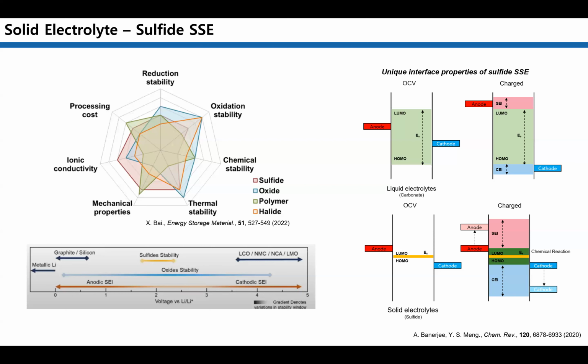In carbonate electrolyte systems like NCM and graphite, the HOMO and LUMO levels are outside the stability window, resulting in chemical instability. However, in solid-state systems, sulfide electrolytes in particular are theoretically unsuitable because of their low stability window. This creates a challenge, as sulfide electrolytes are chemically incompatible with cathode material. But interestingly, their low stability allows them to operate reliably under battery operation conditions. The decomposed components act as a buffer layer that prevents further electrolyte contact with active materials, thus maintaining conductivity.